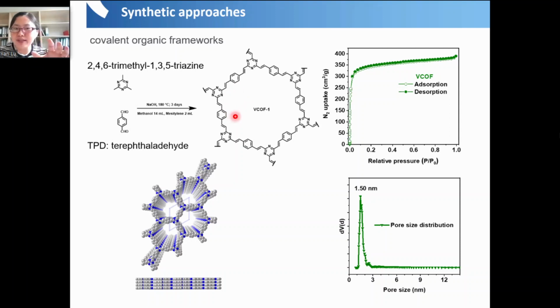So this is only one unit. This is computer simulated. You will see this is only one of these porous structures. So you will get a very nice organic porous material, each with these very defined pores. And from the gas absorption desorption method, you can see here they get a very well defined pore, and it has a diameter around 1.5 nanometers. So this is like one of this pore size.